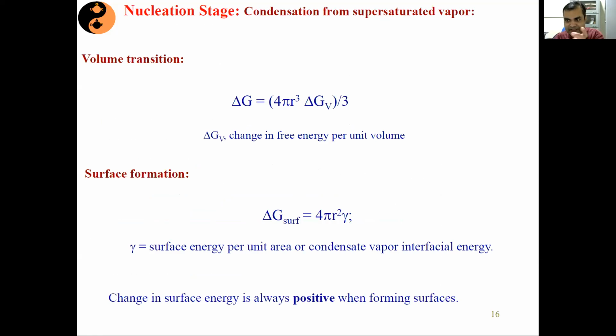Please remember, whenever that nucleation is taking place, nucleation means what? Nucleation means you have different evaporants coming together and they are forming some kind of size and shape. And when that shape actually takes place, that means it has certain surface, that means it has certain volume. So either to create a surface or to create a volume, we need to have sufficient energy available. Right? So we know that the surface energy is given by 4 pi r square times gamma, which is nothing but surface energy per unit area, whereas volume energy is given by 4/3 pi r cube delta GV. Delta GV is nothing but the change in free energy per unit volume.